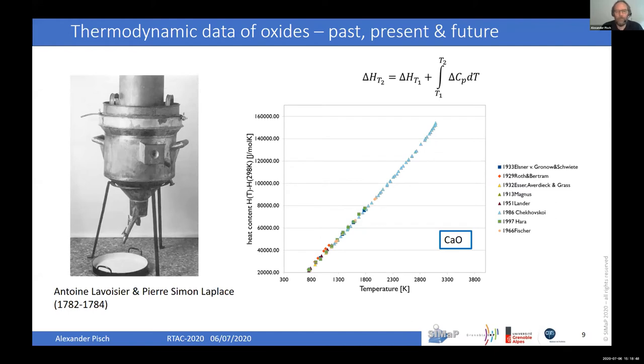When it goes to high temperature, again, you have one way of doing it, which is the heat content measurements. So you measure H at a higher temperature minus H at room temperature. You can use two types of calorimeters, either direct calorimetry, which means you start a sample from room temperature and drop it in a calorimeter which is heated. This is limited to 1500 Celsius.